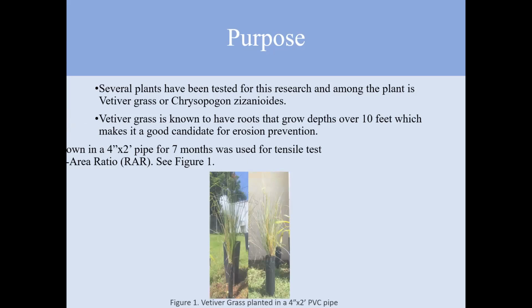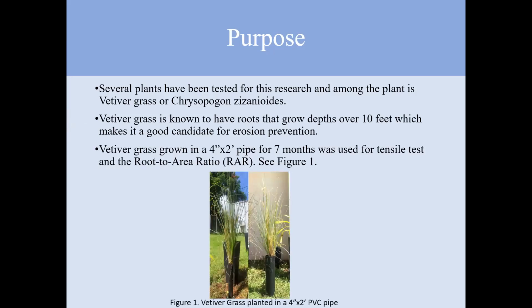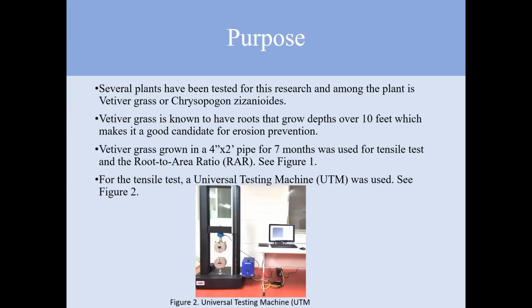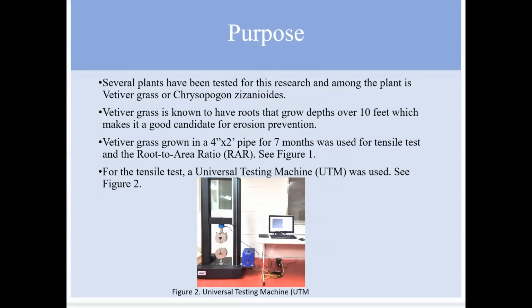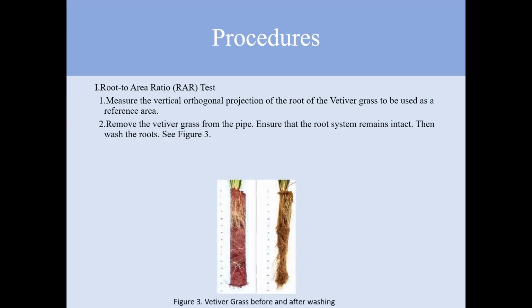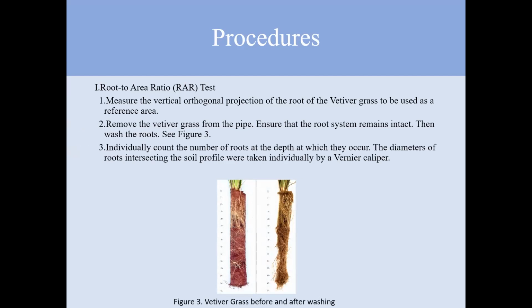For the RAR test and the tensile test, we used vetiver grass that was grown for 7 months in 4-inch by 2 feet PVC pipes. The tensile test was done using the Universal Testing Machine, UTM for short. For RAR, we began by measuring the vertical orthogonal projection of the vetiver grass to be used as a reference area. Then, we removed the vetiver grass from the pipe and ensured that the root system remains intact. Then we washed the roots. After washing, we individually counted the roots at the depth at which they occur, and then the diameters of roots intersecting the soil profile were taken individually by a vernier caliper. We recorded the RAR values at 5 centimeter depth increments.